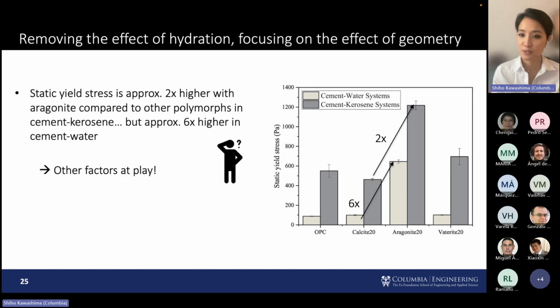So that explains a little bit, but if you look at the values in the cement kerosene system, the static yield stress compared to, let's say, calcite, aragonite was 2 times higher, okay? But if you look at the cement water systems, it was 6 times higher. So this pointed to us that geometry isn't the only factor at play. So there's more happening. And of course, we looked into the impact of hydration.